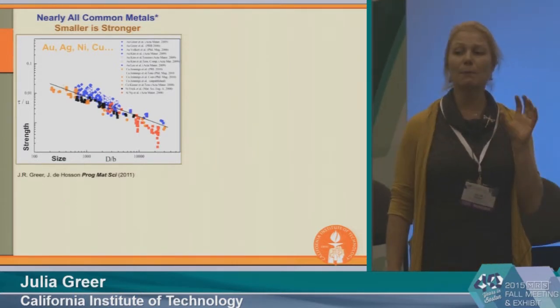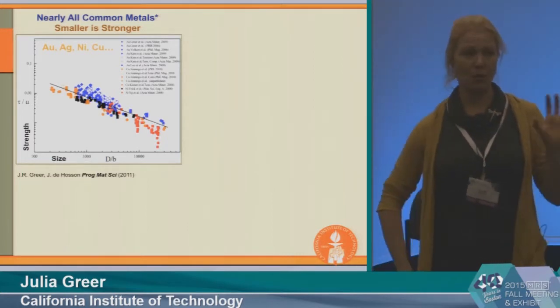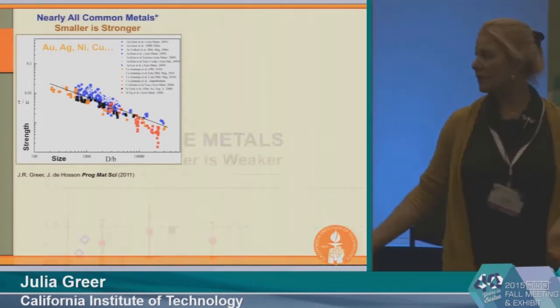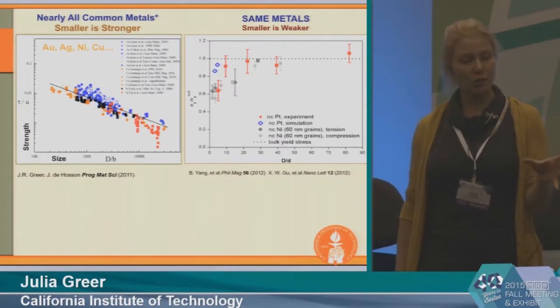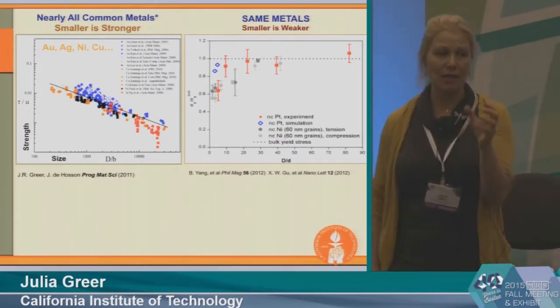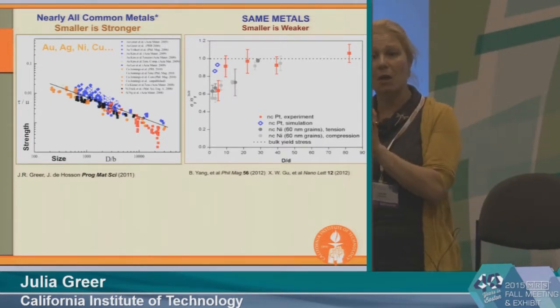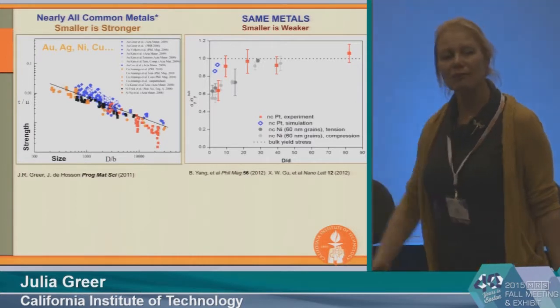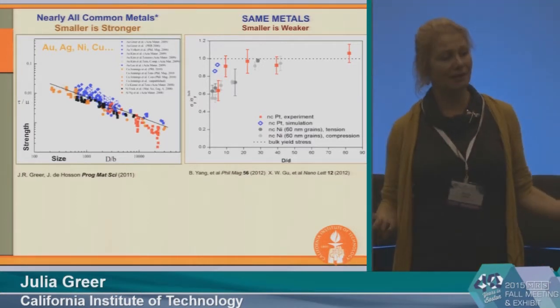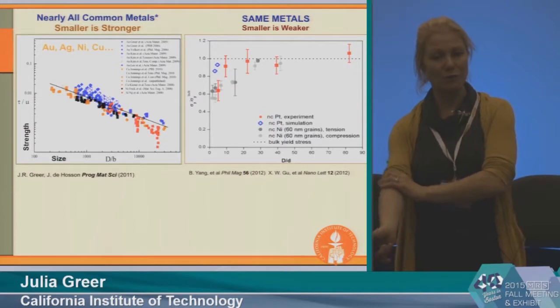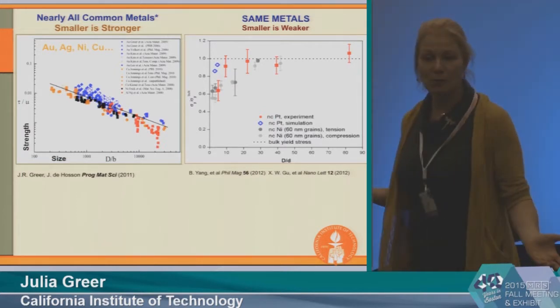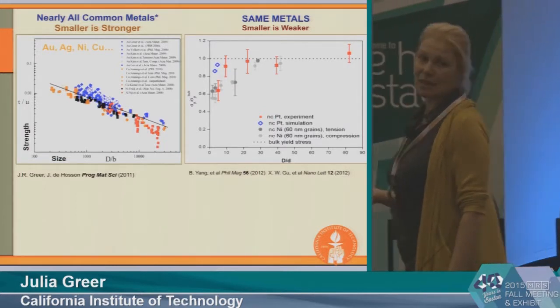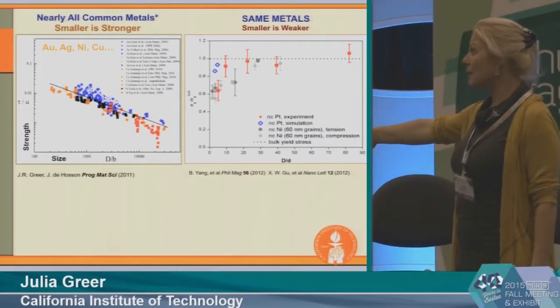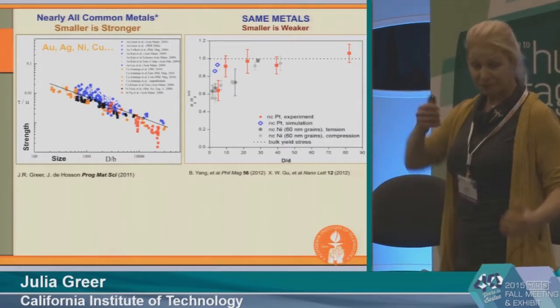Now, if you were to deposit these very same metals, gold and nickel and platinum, in a slightly different way, such that the microstructure that you get is nanocrystalline, so you have these very small grains, all of a sudden this effect is reversed. So it's exactly the same material that has a different atomic level microstructure, and now all of a sudden smaller is weaker. It's a more modest effect. It's not on the log-log plot, but it's still real. It's a pronounced size effect.